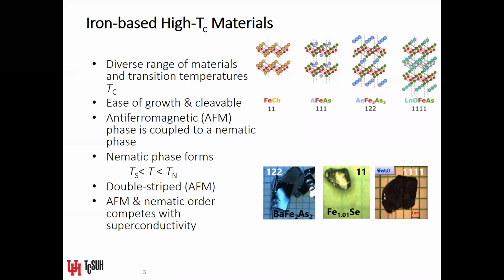What all of these compounds have in common is that there is an iron layer that is bonded to some arsenic atom or chalcogenide atom above and below the iron layer in an alternating fashion. So what you want to see in these four atomic models is a commonality in the iron pnictide or iron chalcogenide layer, given by the green and red, almost tent-shaped layers. A great many of the iron-based superconductors are fairly easy to grow, and they are also cleavable. The ease of growth has helped to accelerate the study of these materials. If you compare the growth of the iron-based materials to something like the copper oxide superconductors, the material handling and preparation is a lot easier.